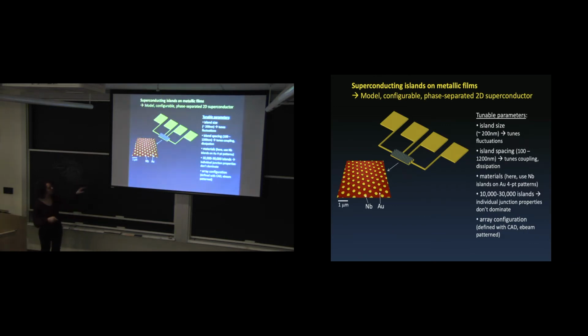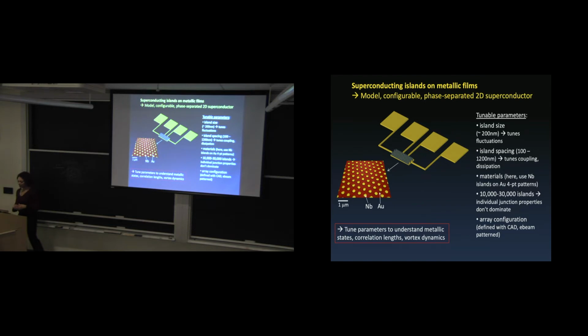So here's what it looks like. There's another AFM image of the niobium islands on the gold substrate with our 4-point measurement. And because we do everything with lithography, it's all tunable. We can tune the island size, the island spacing, all the properties, the array configuration, and really start studying parameters that are due to these metallic states and vortex dynamics, as I'll mention.